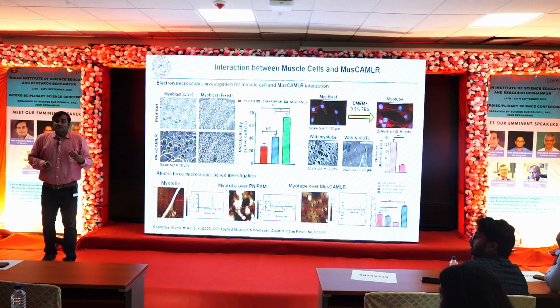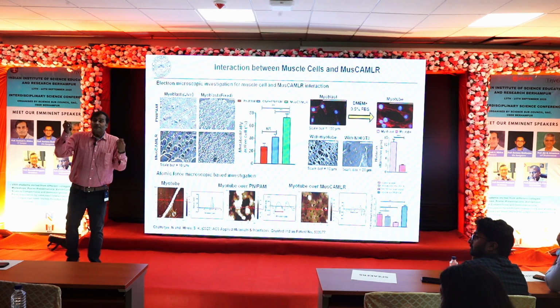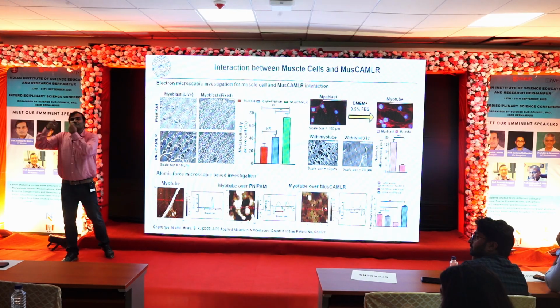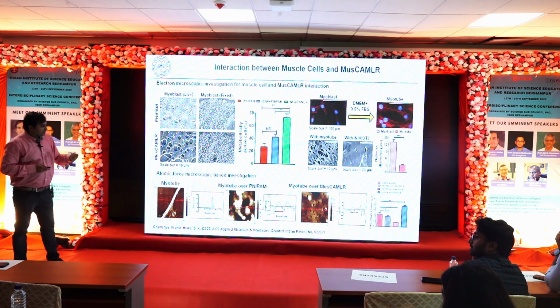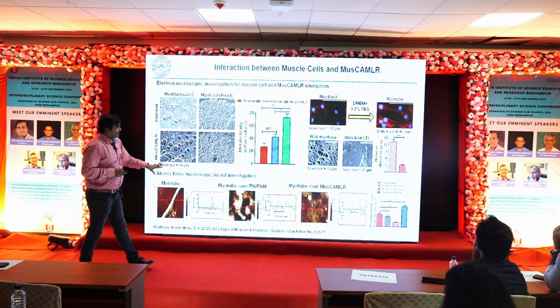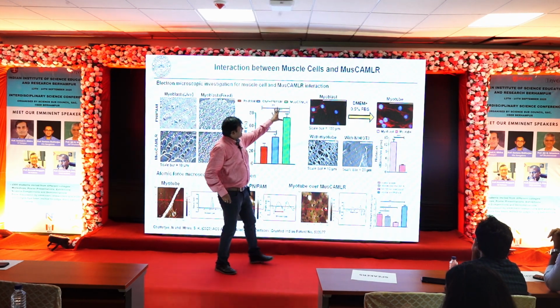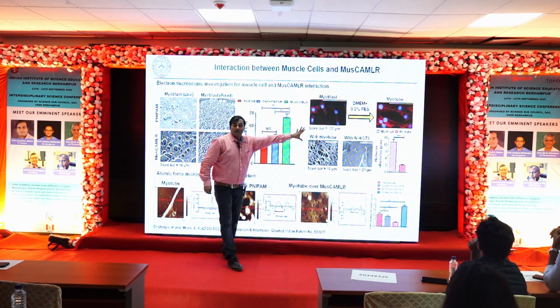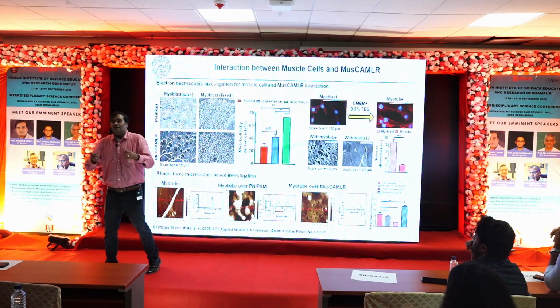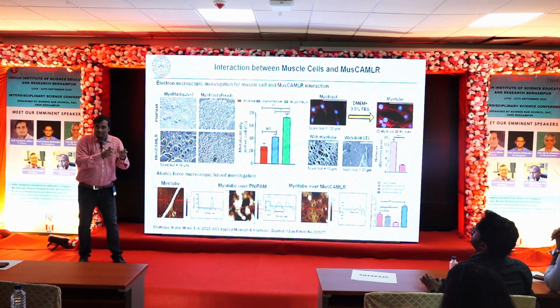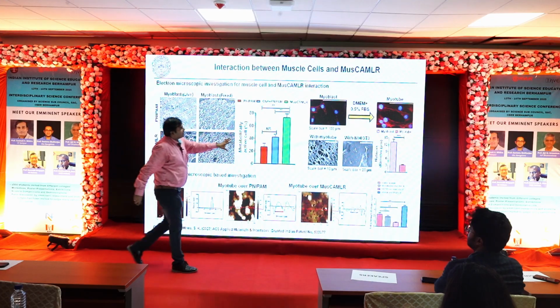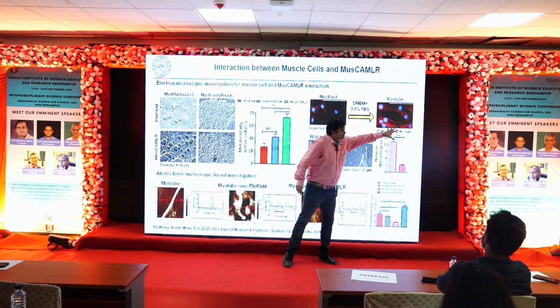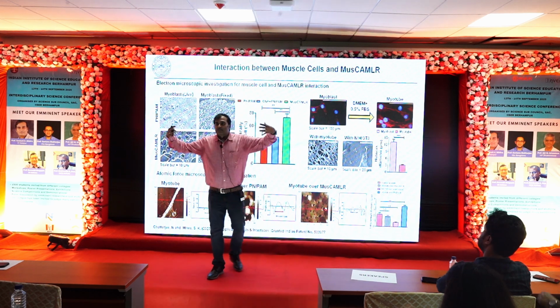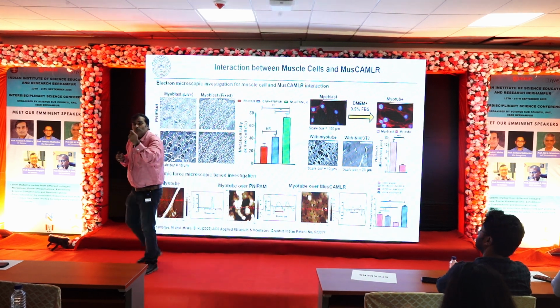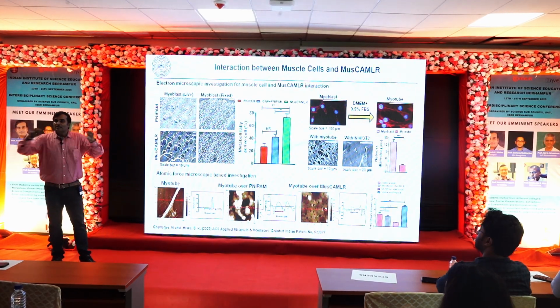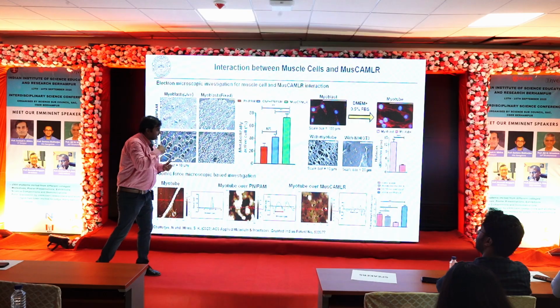Now we got curious about why that is happening. If it is just the material interaction, then it should absorb even with the dead cell and other materials, but that did not happen. We first tried to find out whether the change from myoblasts to myotube is happening or not. There is a protein which is present when blast cells convert into myotube, and we found these extensions, you can see, that are because of the fusing of the cells. When muscle cells fuse, there will be more than one nucleus per elongation. That tells us that fusion has happened and it has now converted to myotube.